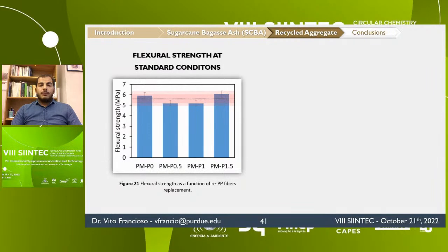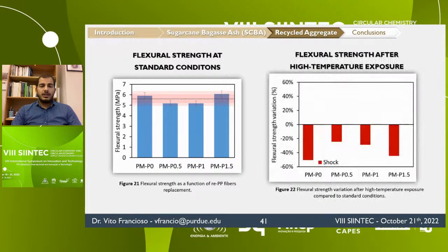Now, the use of recycled polypropylene fibers did not significantly impact the flexural strength under standard condition, so the unexposed samples. The variation with respect to the flexural strength of the reference mortar is within 15%. However, as we can see in these other figures, when I'm representing the variation of flexural strength after high temperature exposure compared to the strength under standard condition, the polypropylene fibers decrease the loss of flexural strength produced by high temperature exposure and thermal shock.